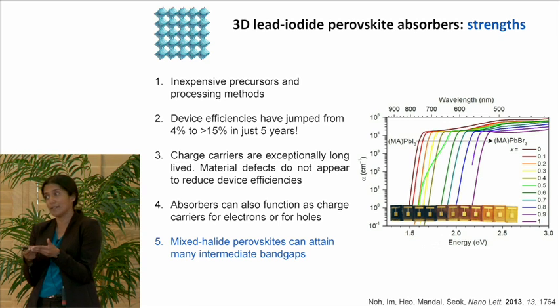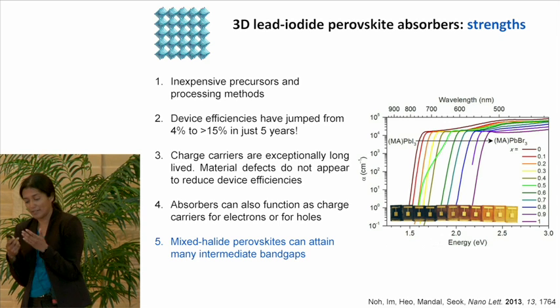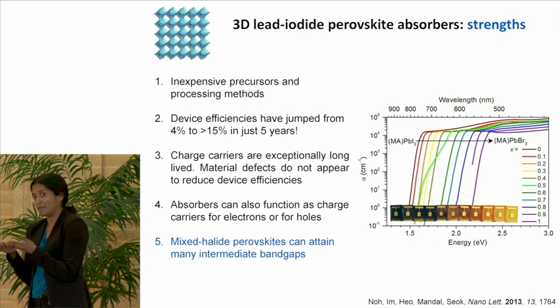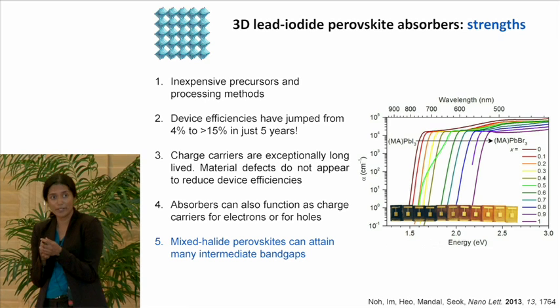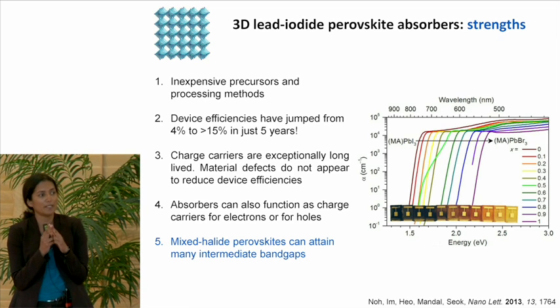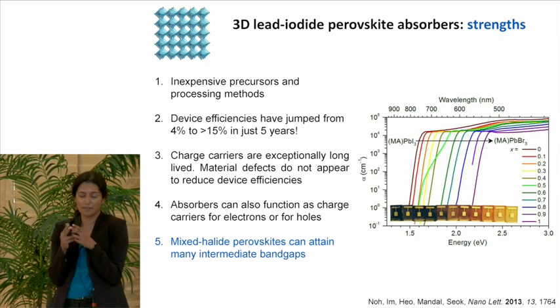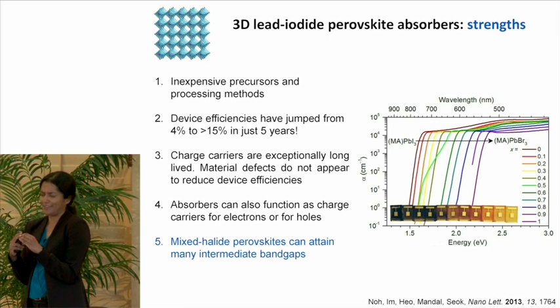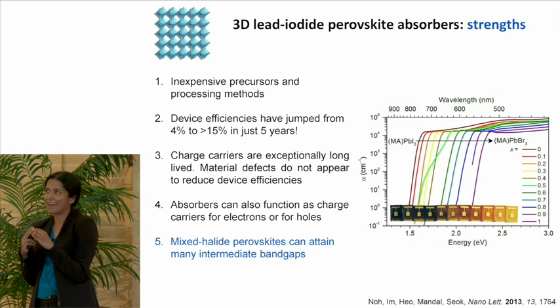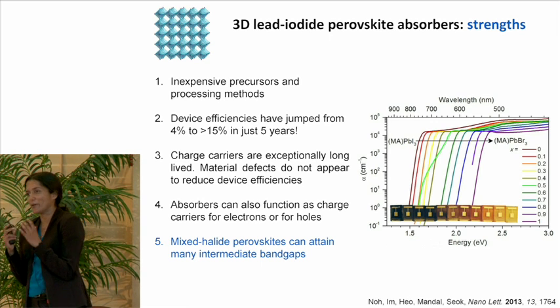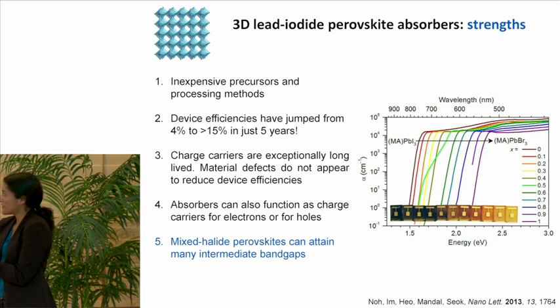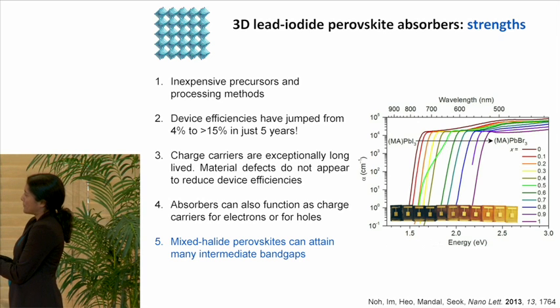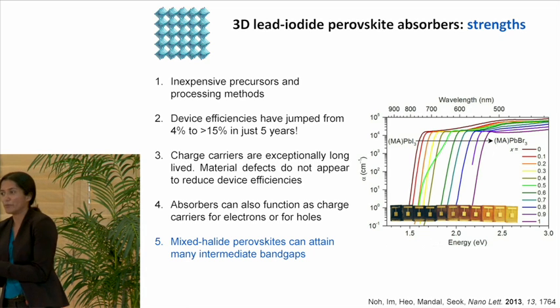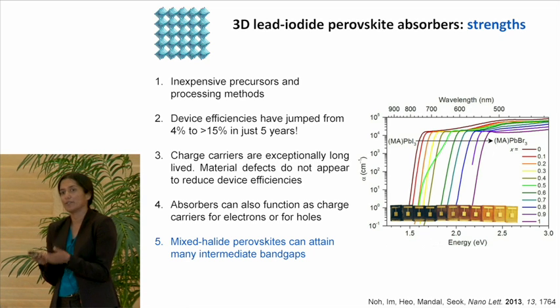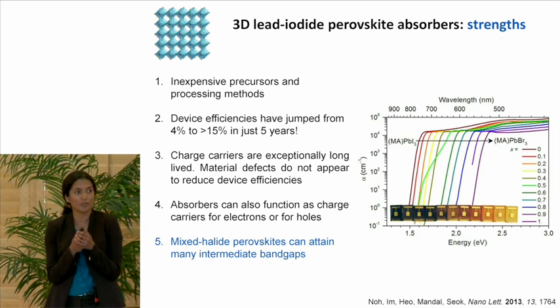With respect to solar cells, Mike mentioned that his group works on tandem devices, and they have indeed shown that tandems can work very well. In a two-absorber tandem device, the band gap of the higher energy absorber has to be about 1.9 eV. So with lead iodide alone, we get a band gap of about 1.5 eV. So in order to get to 1.9 eV, one potential strategy is to incorporate bromide into this structure.